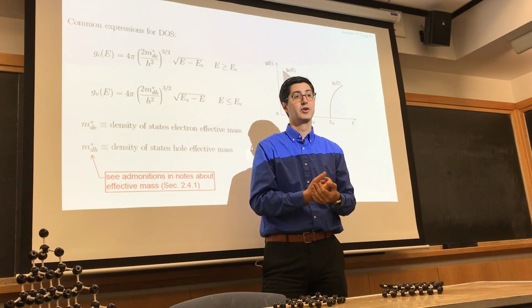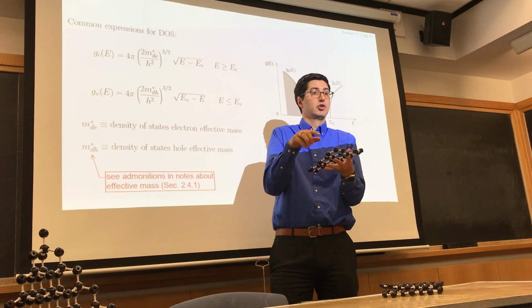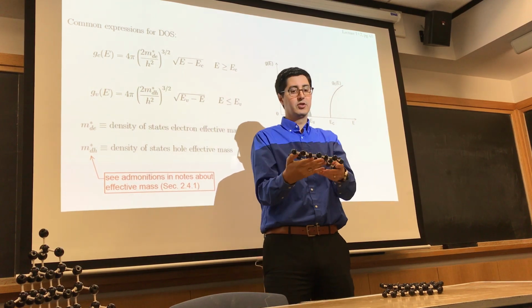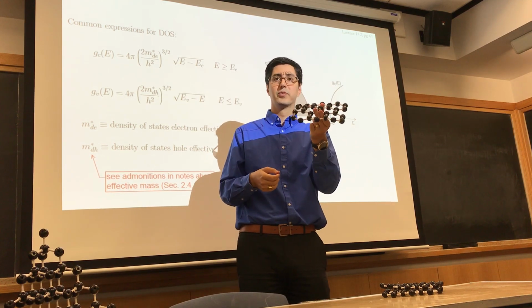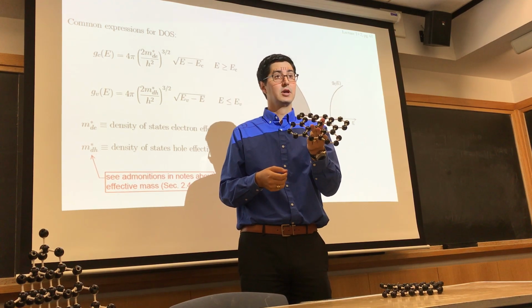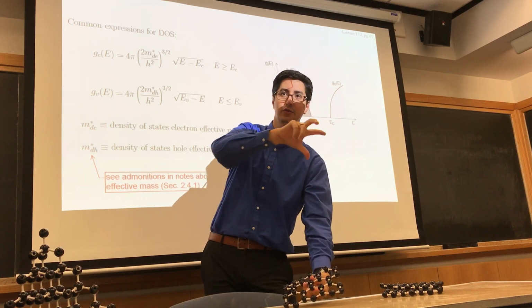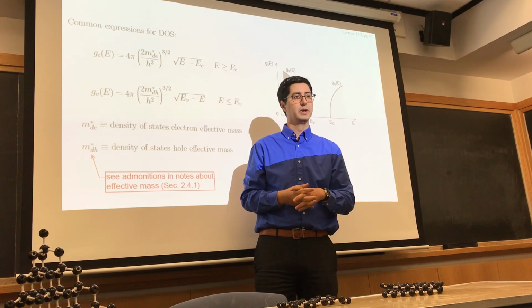but if you look over a large enough area, probabilistically, sometimes you'll have a single layer. And what's incredible about it is you can actually see it optically. There's a little contrast with that layer. Your light setting has to be correct, but you can actually see a single layer absorbs about 2 to 3% of the light. So you can see that contrast with your eyes. It looks like a little shadow in that region, not a super dark shadow,